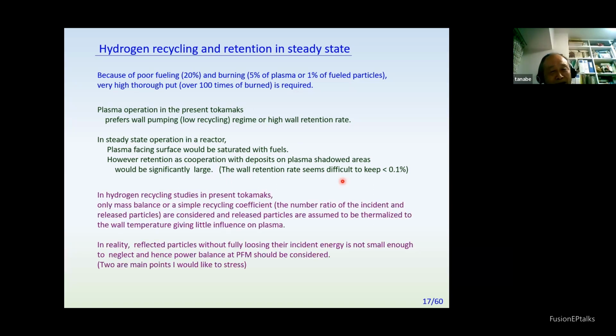In hydrogen recycling studies on present tokamaks, only a simple mass balance or recycling coefficient - the ratio of input to output - is considered. Released particles are assumed to be thermalized at the wall temperature, giving little influence on the plasma. But in reality, reflected particles without fully losing their incident energy are not negligible, and hence power balance at the plasma-facing material caused by hydrogen cycling should be a concern.